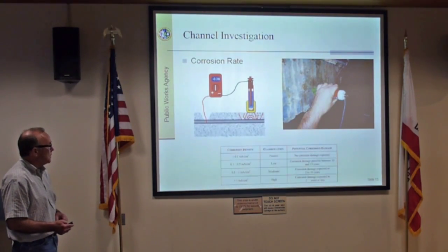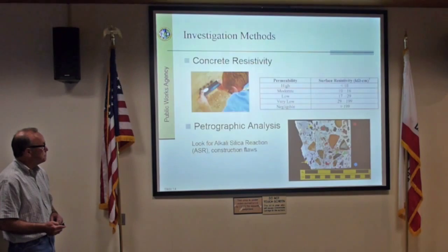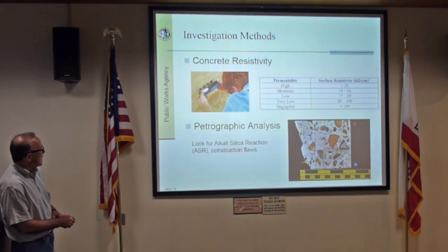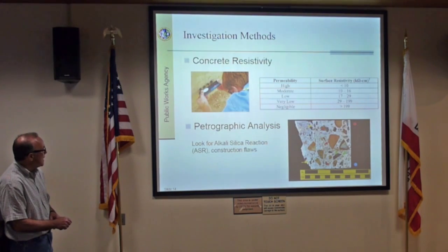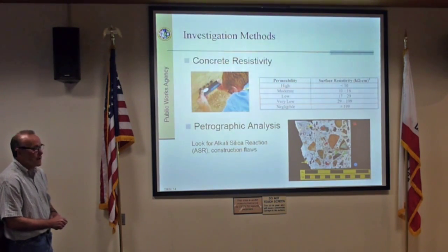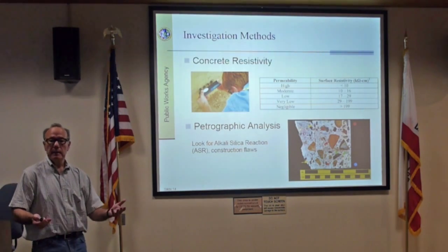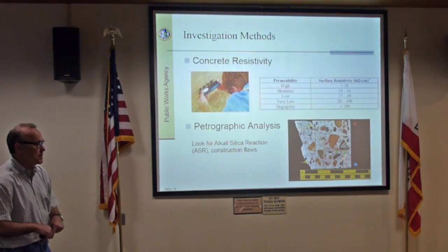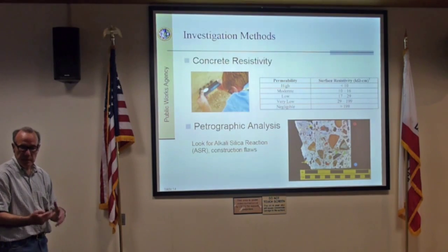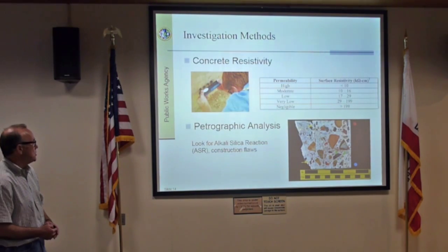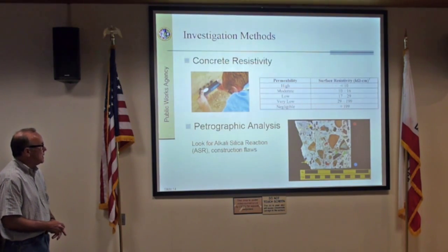So we have to do some interpretation of it. The other thing we can do is use this little concrete resistivity device. We can put it on the concrete. It really tells us how conductive the concrete is. If it's very wet, it drives down the resistance, which means it's very conductive for electron flow, for corrosion. If it's very dry, that would be the case where the resistivity is in kiloohms per centimeter.